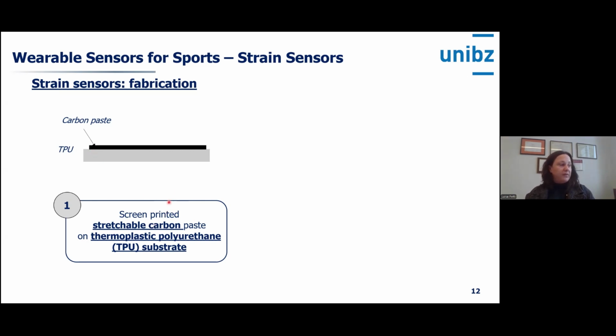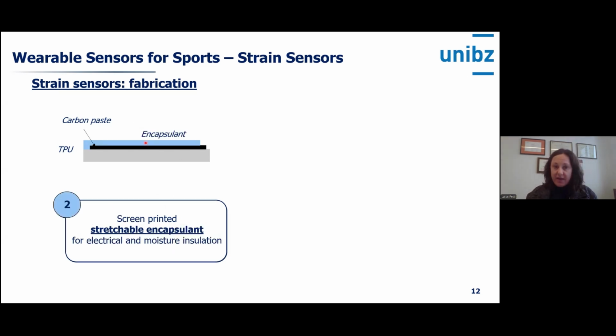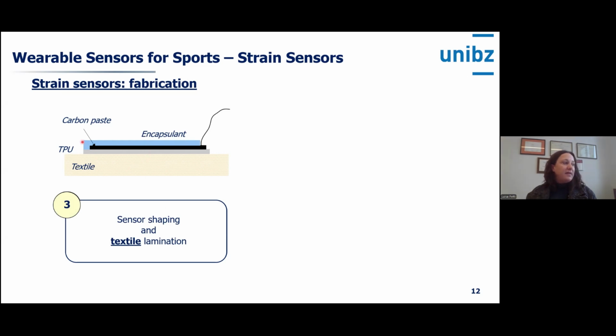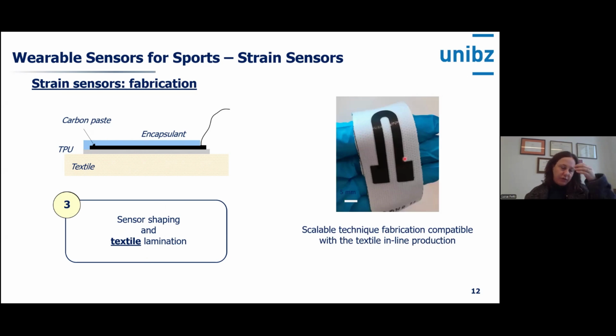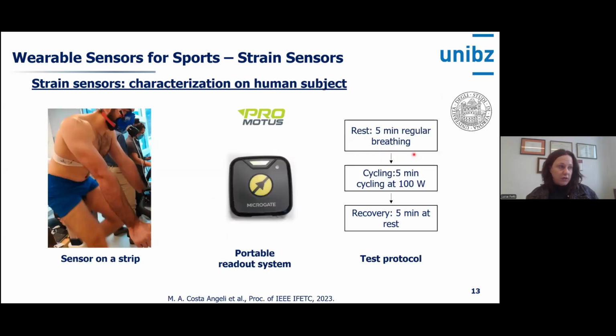So first, screen printing a stretchable carbon ink on a thermoplastic polyurethane (TPU) substrate, continuing with printing an encapsulant, and then transferring and heat laminating the TPU substrate onto the textile, shaping it and laminating it. That's the result of the first prototype, with this U shape that was designed in order to have the desired strain characteristic, and we integrated this also into a t-shirt.